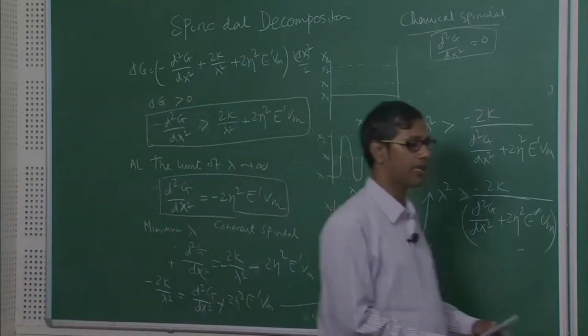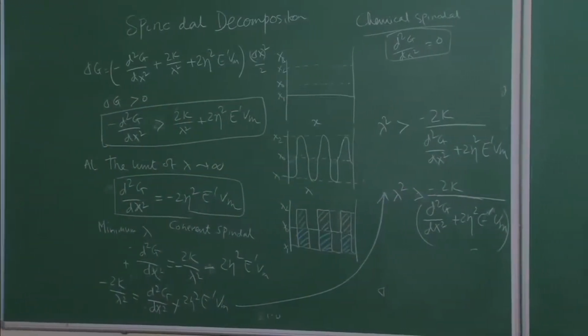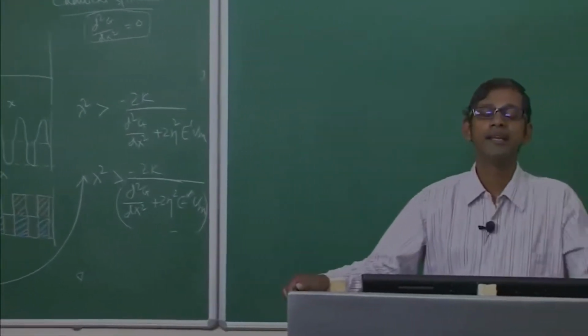Okay, so that is the crux of this lecture today. So what did we discuss? We discussed how to calculate the free energies of the system. We discussed how to calculate the chemical part of free energy, the gradient energy term, which is because of the compositional fluctuation developing an interfacial energy, and finally, because of the lattice parameter misfit of the compositionally decomposed regions, we have strain energy. Once you put all these things together, we get the full free energy expression, and that we can then mathematically analyze and find out the different conditions of the